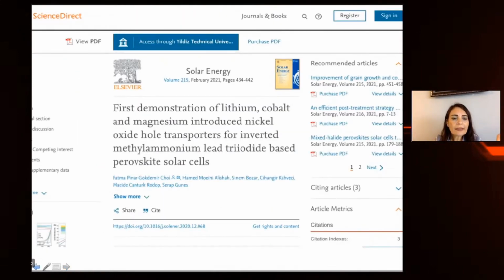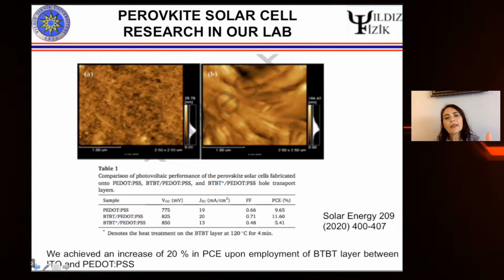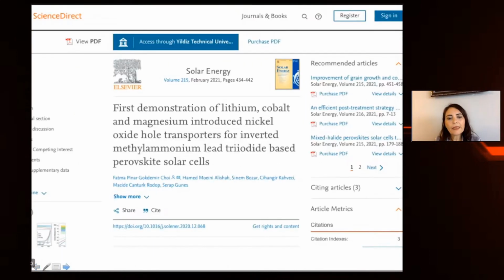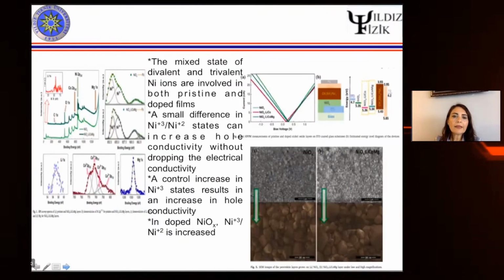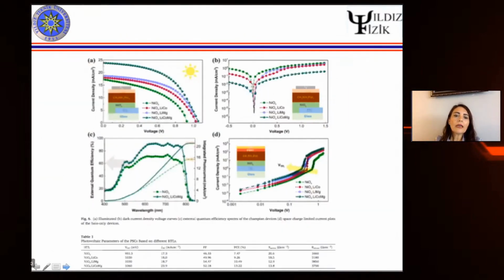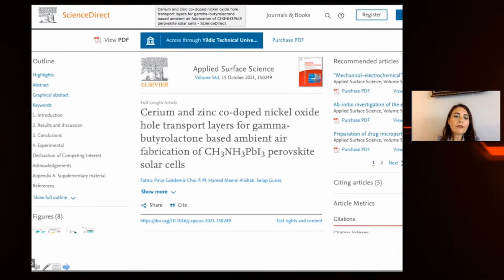As I told you, although Pınar is working on nickel oxide based solar cells, this earlier study was based on PEDOT:PSS, but here this study is based on the nickel oxide as hole transport layer. She doped the nickel oxide with lithium, cobalt, and magnesium. And as a result of this doping, we have realized that the hole conductivity is improved, and also the morphology, the surface became hydrophobic, and we achieved almost 10 to 20% improvement in the efficiency. So later on, she actually doped the nickel oxide layer together with cerium and zinc, and this co-doping also improved.